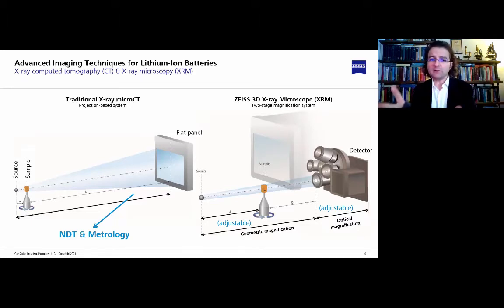But this is not a problem with the 3D X-ray microscopes we have designed at Zeiss because we have something called resolution at a distance, which we use to preserve the high resolution of the reconstructed data even for larger samples.